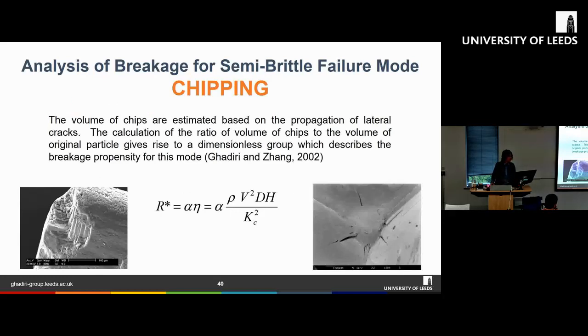Right. So let's move on to semi-brittle failures. Here I want to describe a model for chipping. Here we have the model of Ghadiri and Zhang, and we can see an example showing particles undergoing chipping, where the corner of the material gets chipped off. It's governed by this equation, where R star is the fractional mass loss, and it is a function of the density of the material, V, which is the impact velocity, D, the particle size, H, the hardness, and Kc, the fracture toughness. And A here is a proportionality constant for us to fit the data.